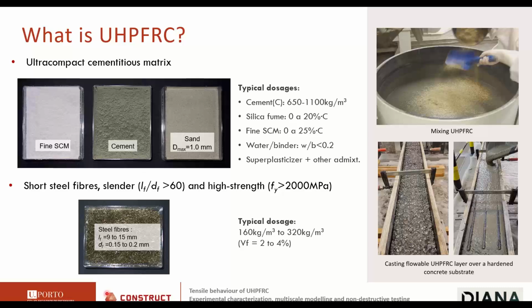So typically the matrix is constituted by cement, silica fume, and then other supplementary cementitious materials like fly ash, limestone powder, many options we have. So the water binder ratio is very small, below 0.2. And of course, we need superplasticizers and other admixtures to make the material self-compacting, which is also a very attractive feature of this material. So it's flowable and doesn't need vibration.